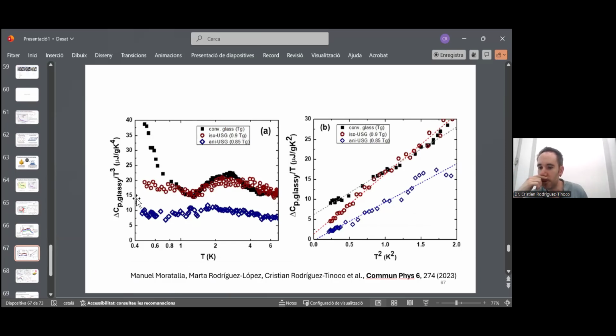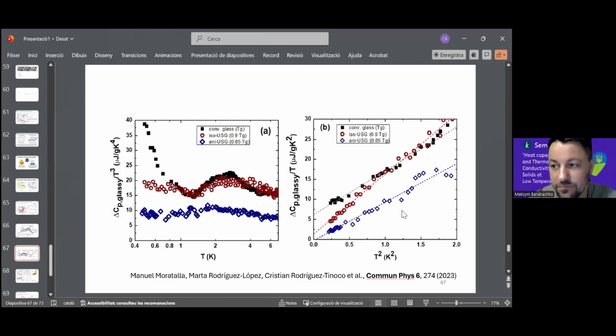Okay, so if you mean a correlation with the Tg of the original material, I would say there is no correlation because in both cases with different Tgs, we have a complete suppression. If you say a correlation with the Tg of the vapor deposited glass, then I would say yes, because the glass transition temperature of the vapor deposited glass depends on the stability. So the higher the stability, the lower the amount of TLS in the system. Okay, thank you.